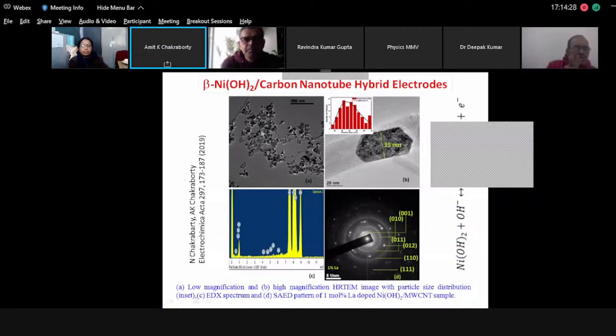These are the high-resolution images where you can see nickel hydroxide, which is hexagonal. These are hexagonal structures, about 35 to 40 nanometers in size, as you can see from the distribution. Further SAED and EDAX confirm their identity. The redox reaction that occurs in the electrolyte is also shown on the right-hand side, showing how the redox, Faradaic reaction takes place. This shows how we developed a composite by attaching nickel hydroxide particles on the surface of the carbon nanotubes. You can see some carbon nanotubes here lying on the bed like this.